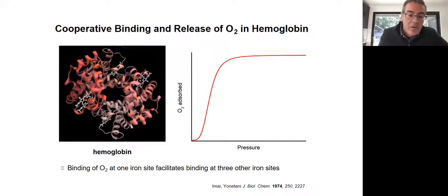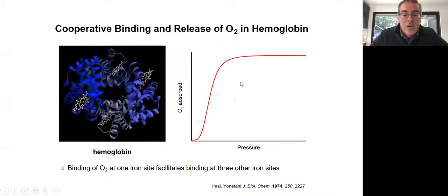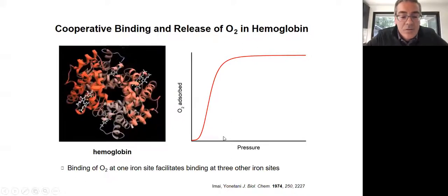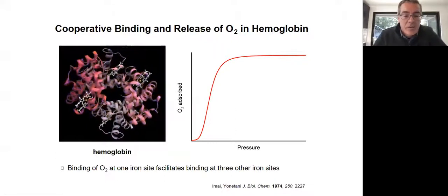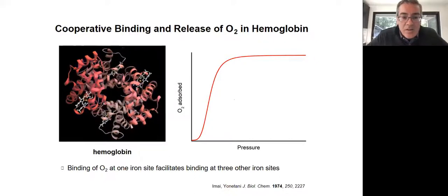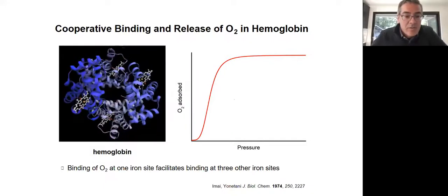And that cooperative adsorption process leads to a step-shaped adsorption isotherm instead of that Langmuir shape that we saw before. And so this allows hemoglobin to bind and release these oxygen molecules with quite a narrow change in the concentration or pressure of oxygen. And that's exactly the kind of thing we'd like to do for having an efficient separation. And nobody realized that this was possible in a dense way in a porous solid material until we accidentally discovered that it's possible for carbon dioxide in an amine functionalized MOF.